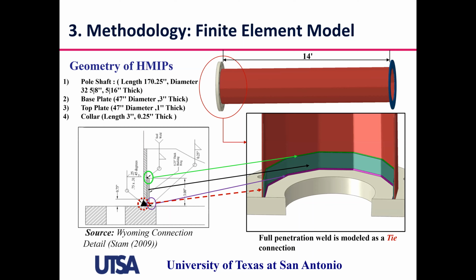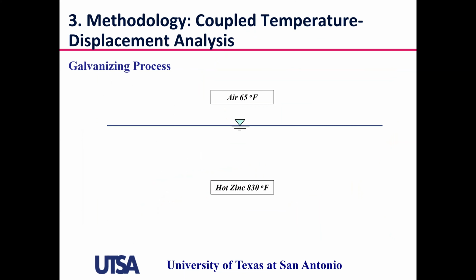And what the Wyoming detail has is a full penetration weld between the pole and the base, and then a backing ring. And this backing ring actually was introduced to improve the fatigue performance, but it didn't consider its impact on crack formation. And so through the study, we also try to capture the impact of the backing ring on the crack formation phenomena during galvanizing.